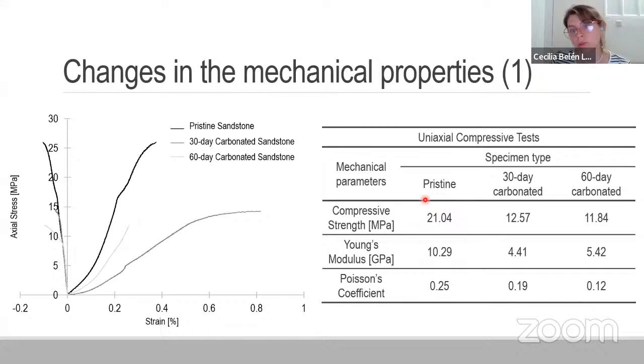There was a more notorious decrease between the pristine and the 30-day carbonated specimen, but the 60-day carbonated specimen also presented this behavior. Another observation was that the Young's modulus was also reduced, meaning there seemed to be a change in the behavior of the rock from a fragile behavior to a more ductile one.